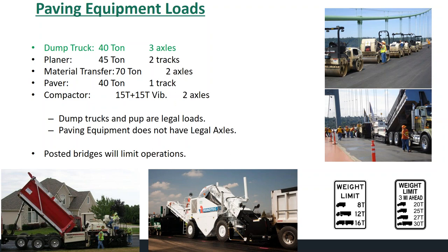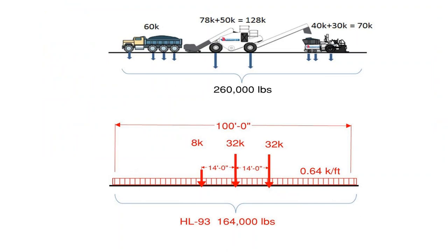And so you can see here, there's a breakdown of the different pieces of equipment. That material transfer vehicle can be very heavy. And on roads, you can tolerate that. On bridges, not so much. So we have to be very concerned and look at the weight distribution on our bridges. You can see here that this typical paving train could be over 260,000 pounds when the design of a bridge in that same span in that same area would typically only be 164,000. So it's much heavier than the original design of even new bridges.